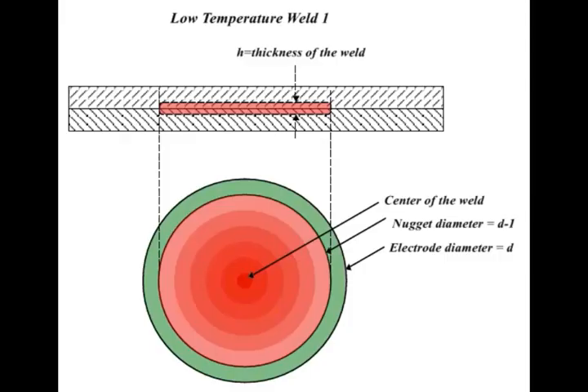From the top looking down, you can see the center temperature is higher than the temperature at the edge of the electrode. The diameter of the electrode is d and the diameter of the weld is slightly less than the electrode diameter. The difference between the electrode diameter and weld diameter is called the transition ring. It is plotted in green. The inside edge of the transition ring is always 750 degrees Celsius. The outside edge of this ring is the ambient temperature.